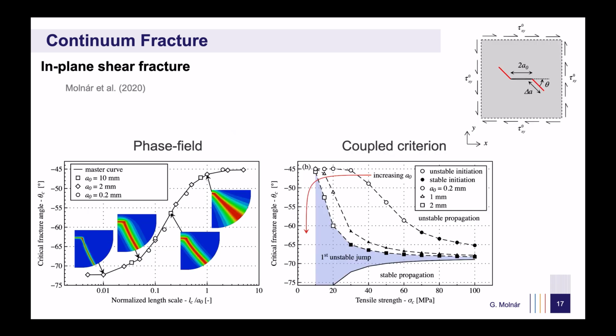For shear fracture, contrary to Irwin's assumption, the crack does not propagate in a self-similar manner. Instead, it branches at a well-defined angle, which depends on the ratio between initial crack size and LC. This angle varies between 45 and 73 degrees. 45 degrees corresponds to the direction of the principal stresses in shear, while 73 degrees is consistent with experimental observations for very brittle materials with very small process zone. And it aligns with the maximum energy release rate direction. The coupled criterion confirms this behavior: when the tensile strength is high, the preferred branching angle is around 70 degrees. However, when sigma c is small, the angle gradually converges to 45 degrees.